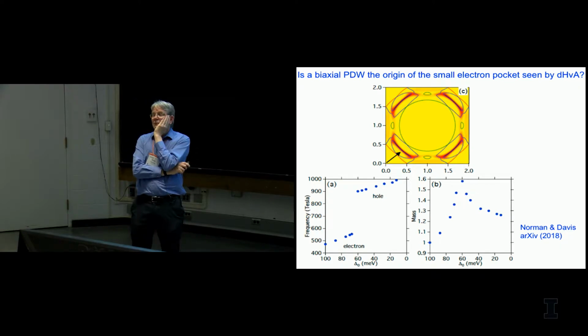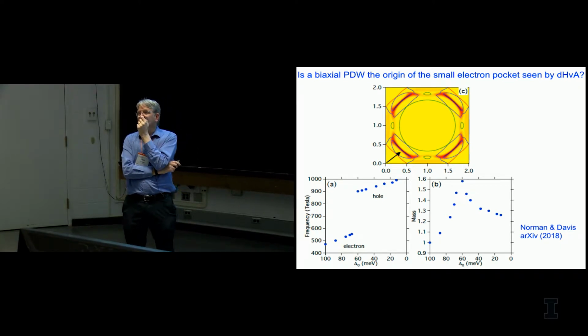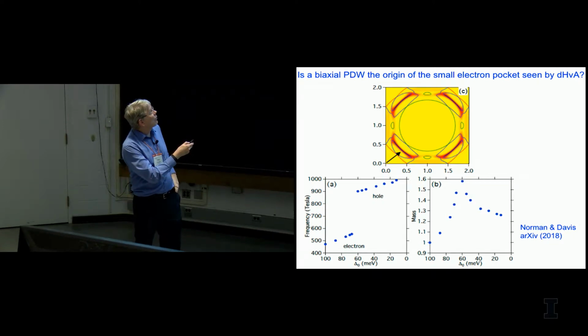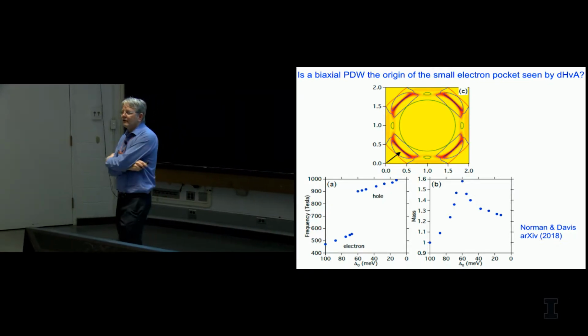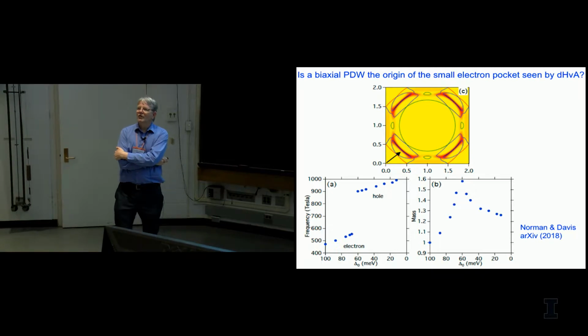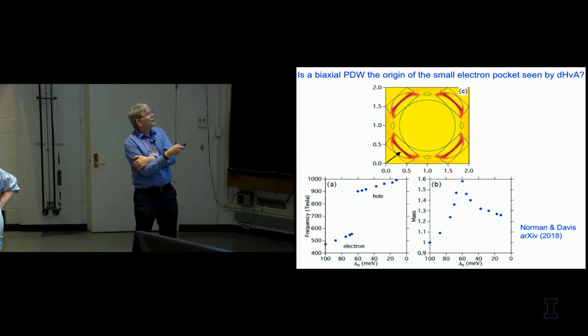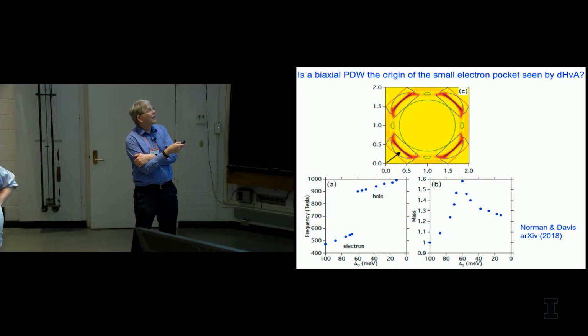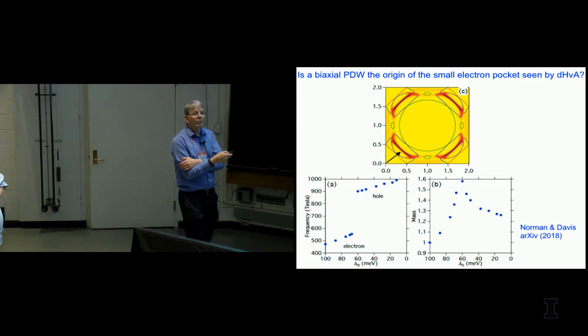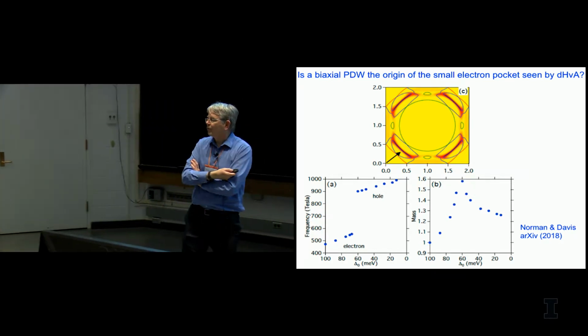If the folding is done by a modulated superconducting phase, it's not clear, because if you look at this so-called electron pocket, this side of the pocket is electron-like, that side is hole-like, and therefore it becomes questionable whether you actually get quantum oscillations from such an object or not. Our contention is, if you look at the thermodynamic free energy, it turns out that only the particle-like content of the state enters the thermodynamic potential, and the particle-like content is non-zero along the whole contour. But there are other proposals that to actually traverse this contour, you have to have an Andreev reflection at these ends, which might work in momentum space, but in real space leads to a loss of current.